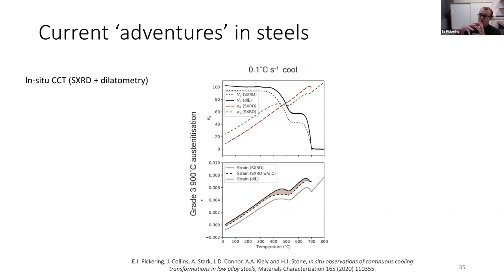When you cool the sample down, if you're measuring a dilatation and there also could be carbon partitioning into the austenite, then the apparent amount of ferrite might not be the actual amount of ferrite, because you've assumed that all the expansion is from ferrite, whereas actually a significant amount of it, highlighted here in the pink, is from carbon enrichment of the austenite. So you've got to be pretty careful with respect to that. But that was some really interesting work that I did at DESY, and also in collaboration with Lee Connor at Diamond.